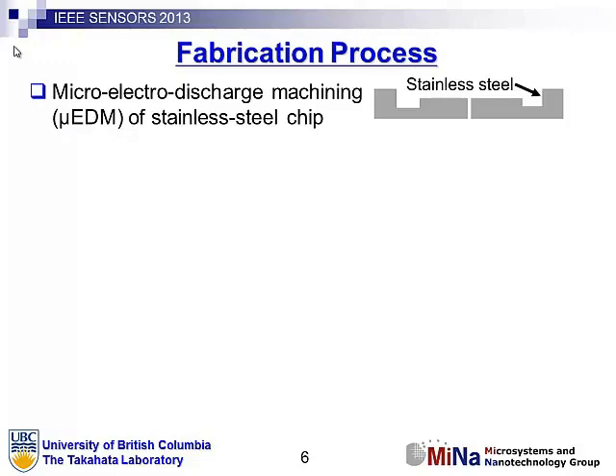Here is the schematic of the fabrication process. It begins with electro discharge machining of the stainless steel substrate. So if you're not familiar, this is not a widely used technique, but it essentially takes a tungsten needle and applies a negative voltage to it as you apply a positive voltage to some conductive material you want to machine.